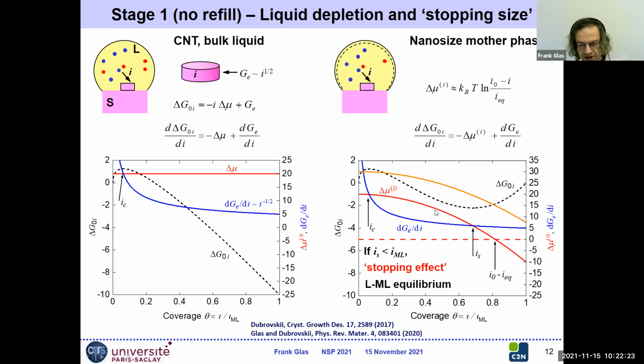And the second thing, of course, is that if we start by chance from a higher content of arsenic in the liquid, that's the orange curve, it might be that, yes, chemical potential will decrease due to depletion, but it will not cross the derivative of the edge energy before we complete the monolayer, coverage equal 1, in which case we won't get this equilibrium. So what happens here? Here we expect the growth to stop because we have a stable equilibrium. Of course, this does not take into account the refilling by the fluxes, but at this stage it's legitimate because it's very fast.